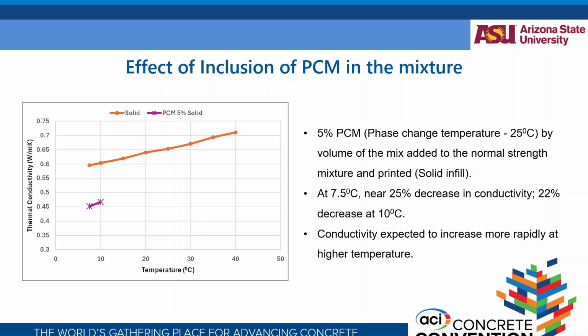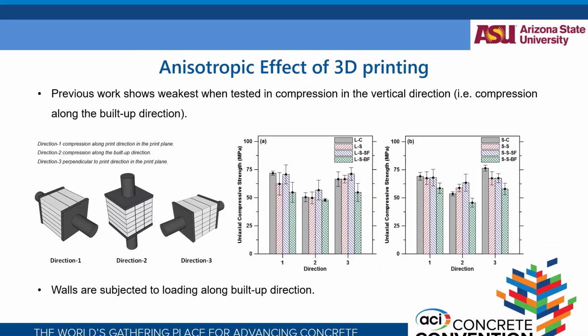We expect that as it goes towards 25 degrees Celsius, it will more or less go closer to the conductivity values for the solid sections. This is what we assume, and we see that based on 2 points. We'll have to see further results to see if it actually does that. So that's more or less on the thermal conductivity part. We are trying to set up a thermal conductivity chamber to see actual heat change, as in this being a wall section for the room, and then do that.